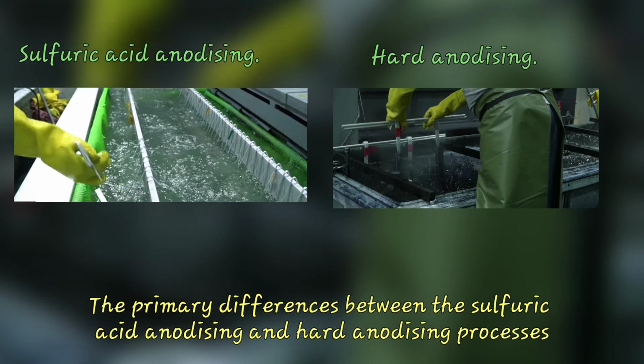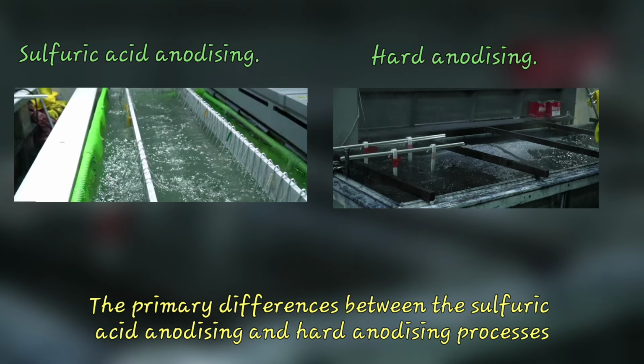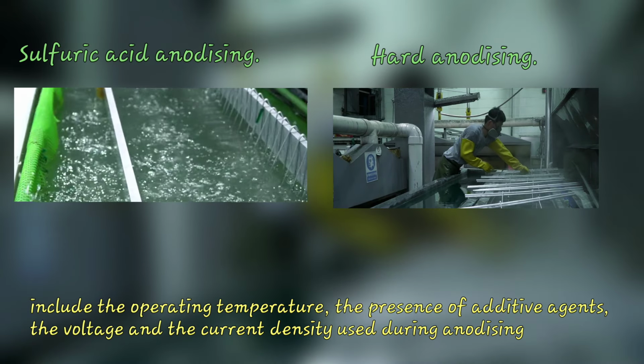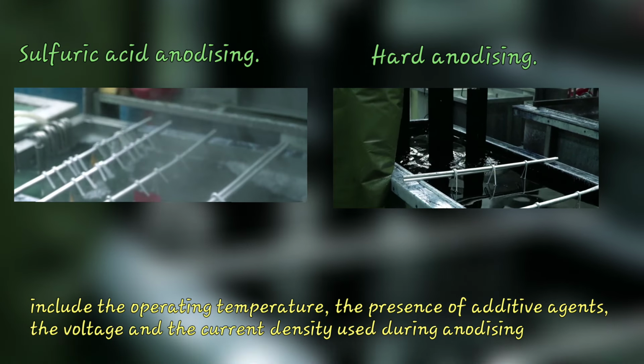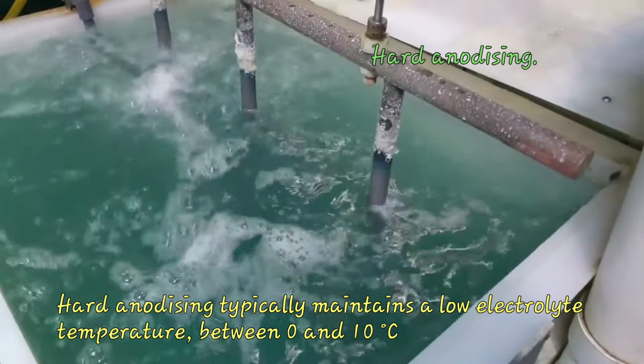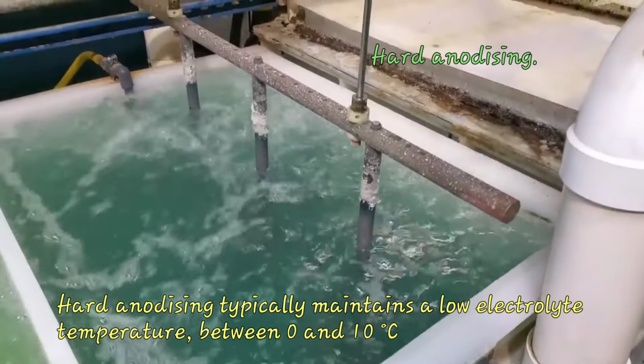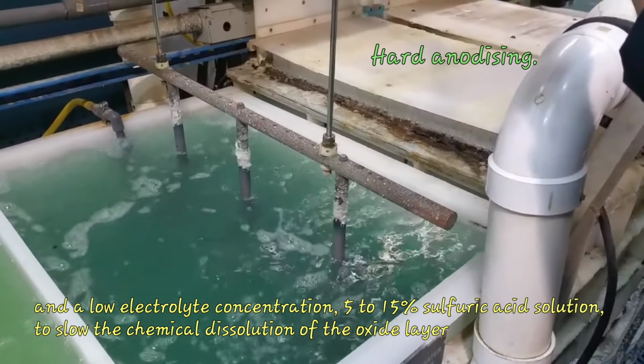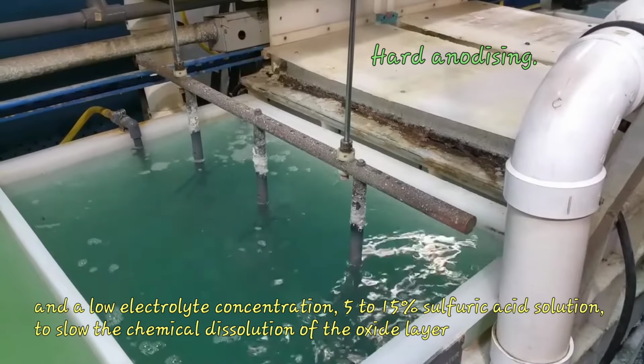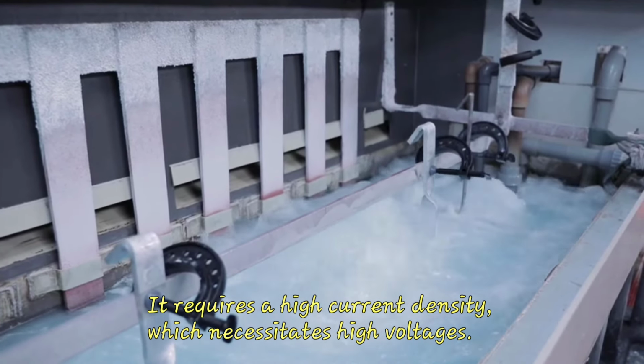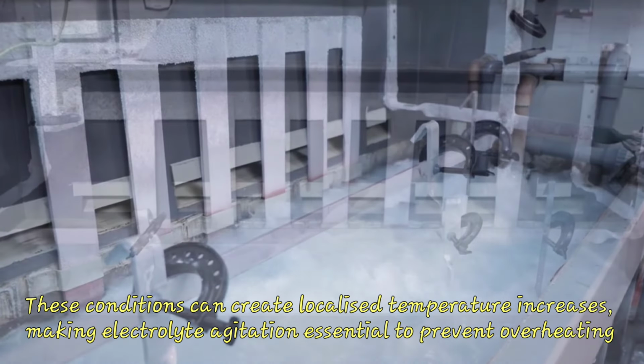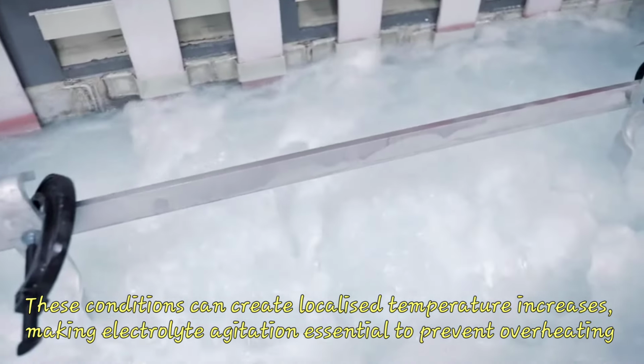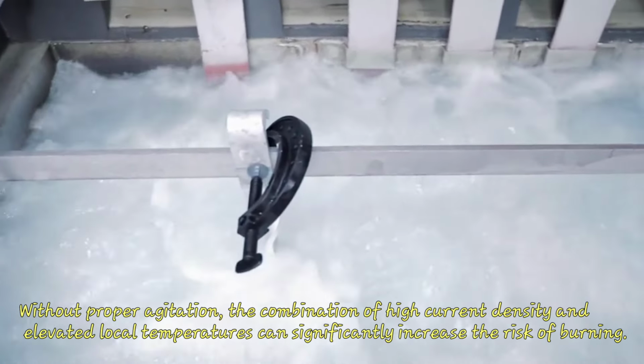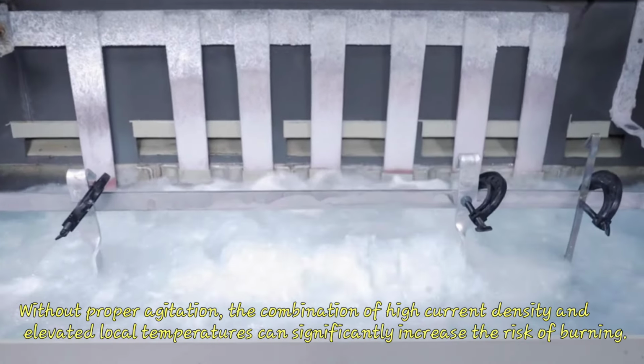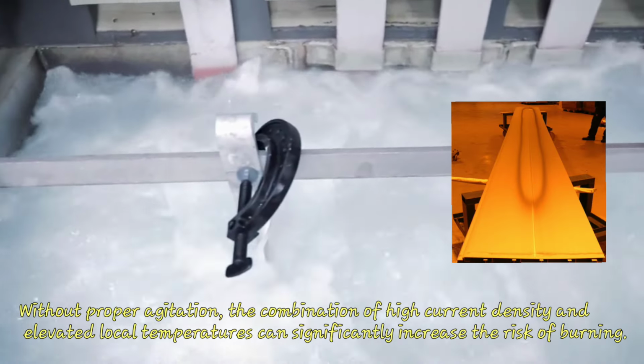The primary differences between the sulfuric acid anodizing and hard anodizing processes include the operating temperature, the presence of additive agents, the voltage and the current density used during anodizing. Hard anodizing typically maintains a low electrolyte temperature, between 0 and 10 degrees Celsius, and a low electrolyte concentration, 5 to 15% sulfuric acid solution, to slow the chemical dissolution of the oxide layer. It requires a high current density, which necessitates high voltages. These conditions can create localized temperature increases, making electrolyte agitation essential to prevent overheating. Without proper agitation, the combination of high current density and elevated local temperatures can significantly increase the risk of burning.